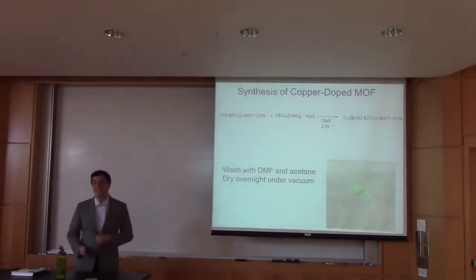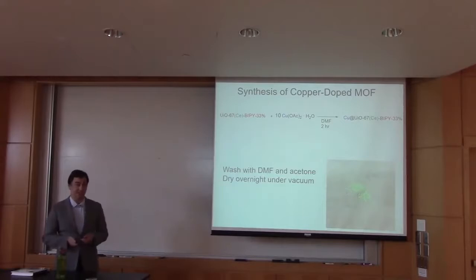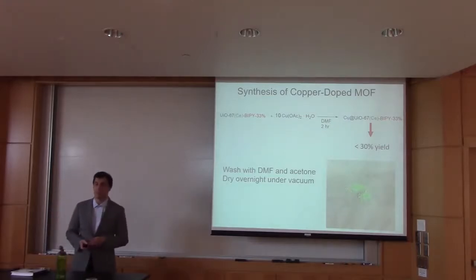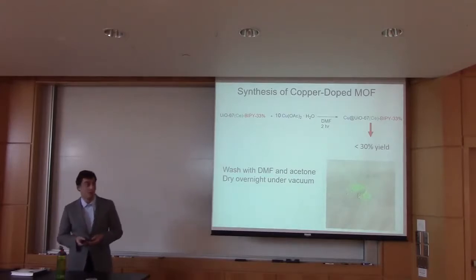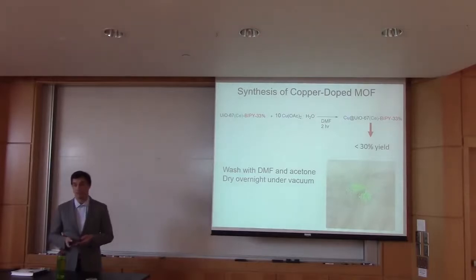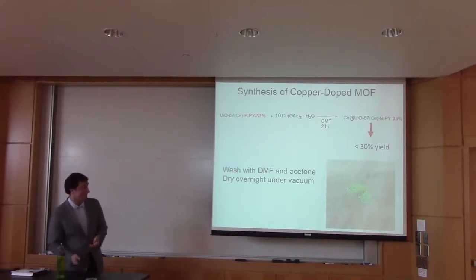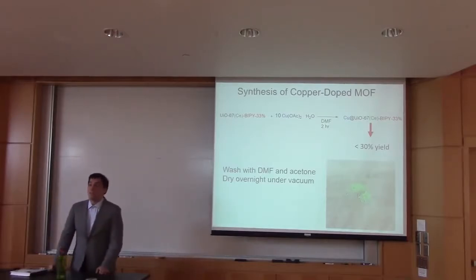The downside to this reaction, although it's very easy to set up and very easy to run, is that we're getting rather low yield, at less than 30%. To some people, this might seem a workable and usable yield, but I was scaling this reaction up from tens of milligrams to the gram scale, and this loss of product was unacceptable, both for the cost of starting materials, which although cheap, add up, and for the cost of my time, as I was running the synthesis repeatedly.